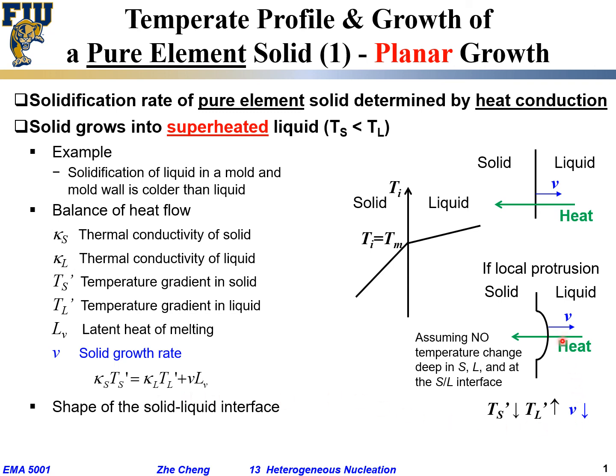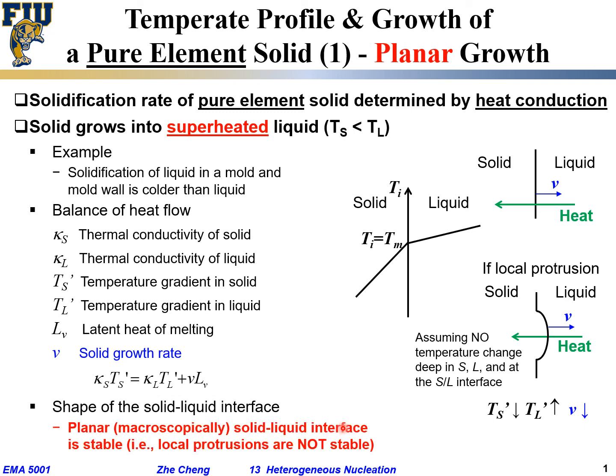What that means is that at the local protrusion, the growth velocity at this location would be slowed down compared with the surrounding planar region. As a result, the protrusion does not grow as fast as the surrounding flat region. The consequence would be that the protrusion would disappear. The planar solid-liquid interface would remain stable, and any protrusion is not stable. Even if it forms, it would disappear or appear less obvious because it moves slower than the surrounding flat region.